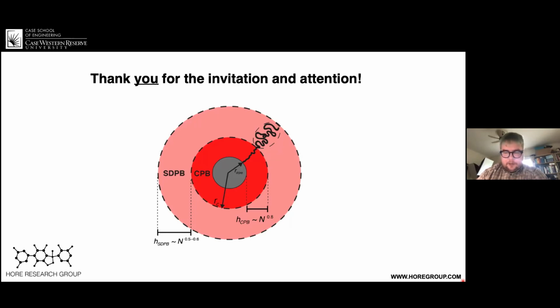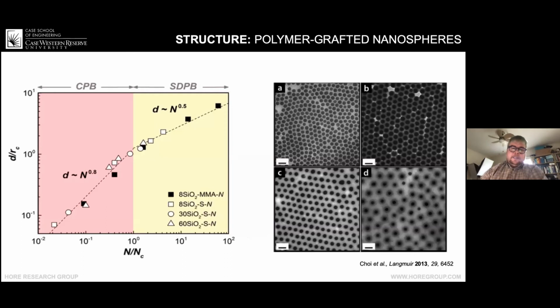So I'm going to go back a few slides and show you something that's not neutron scattering. So this is an example, and you could take the approach that we did with neutron scattering. You could do it in your lab without a nuclear reactor. The downside is that you have to prepare many, many, many different molecular weights of polymer. So you're going to have to synthesize many different batches of polymer grafted nanoparticles.